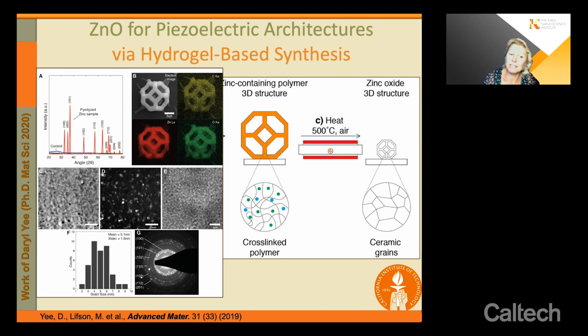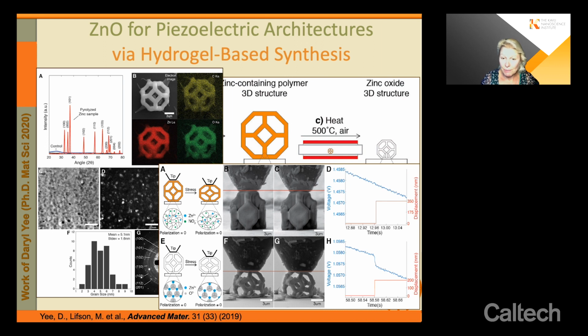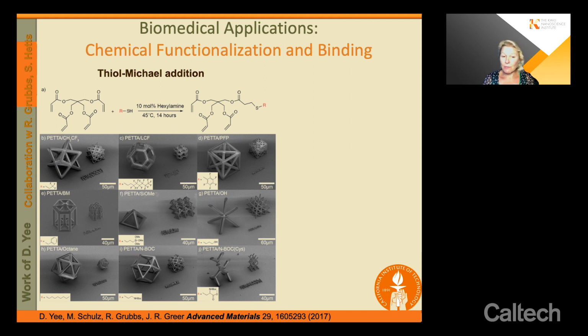For example, zinc oxide has piezoelectric properties. So what you're looking at here is a single unit cell of a zinc oxide nanoarchitecture. And this top part represents the resin, the zinc oxide containing resin, so not pure zinc oxide yet. And when we measure the voltage response, nothing happens. But after this calcination step, when we only have the zinc oxide containing architecture, you can see that when we change the displacement by about 200 nanometers, we observe an unambiguous change in the voltage. So it is possible to create very complex form factors of piezoelectric materials and then to construct and utilize them in devices.